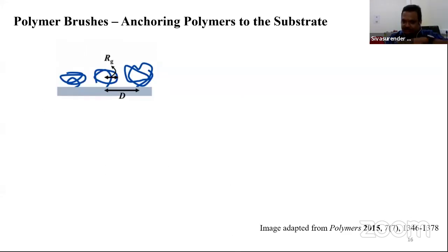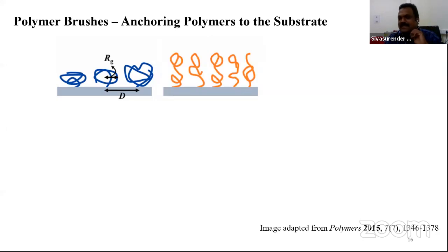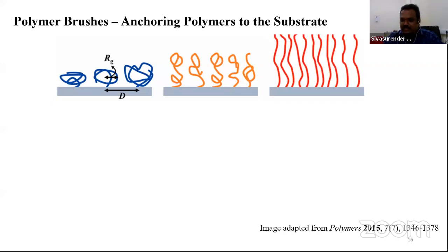Now I'm going to take a substrate and attach polymers on this substrate. One of the ends is going to be attached to the substrate, and the remaining end can still perform the random walk, right? When these polymers are well separated, they all perform a random walk, the entropy is maximized, they're all happy, right? Now let us think about increasing the density of these attachments more. The moment you start increasing the density, the polymers start meeting at their envelope volume, so the steric repulsion, the Coulombic repulsion between the monomers, starts coming into the picture. Then you increase the density so much that, because of the repulsion, these polymers start stretching themselves, and they go out of equilibrium because of the way you created this system, right?